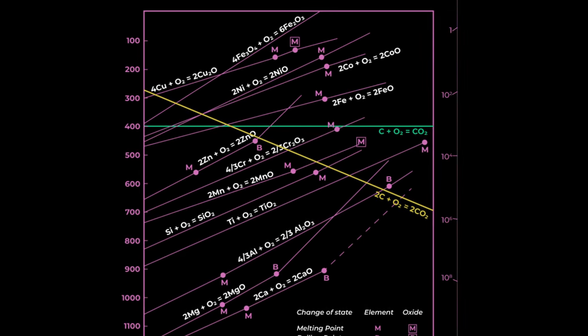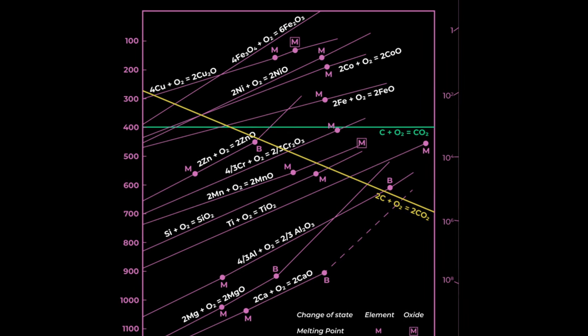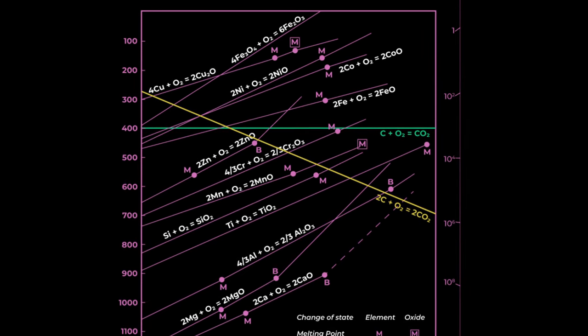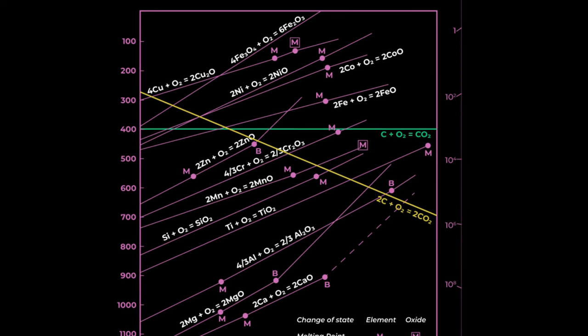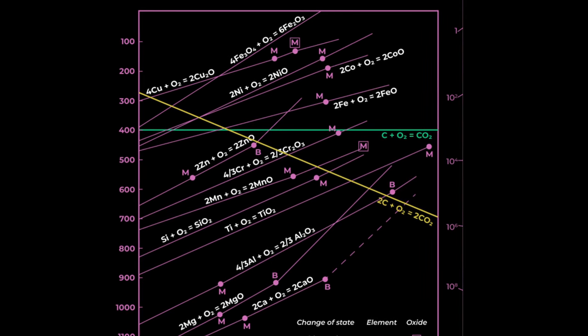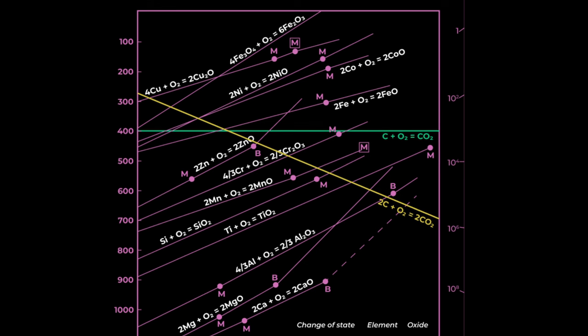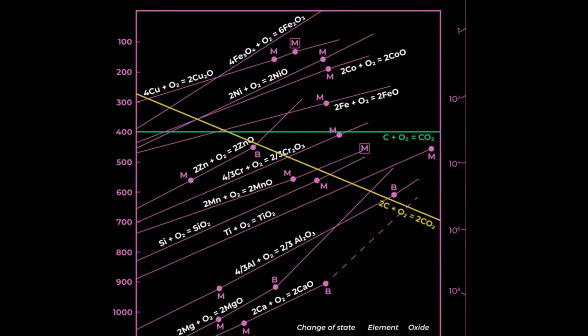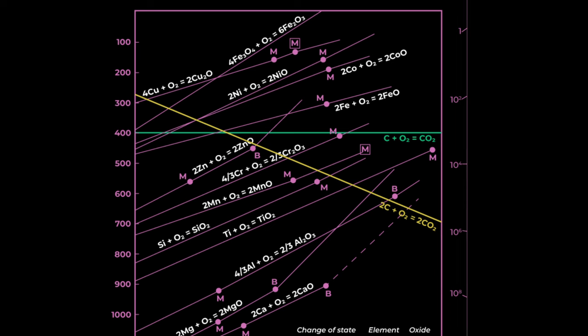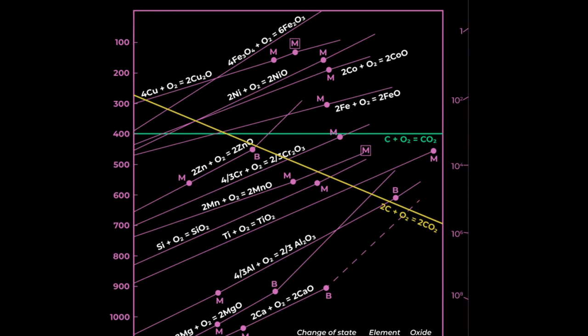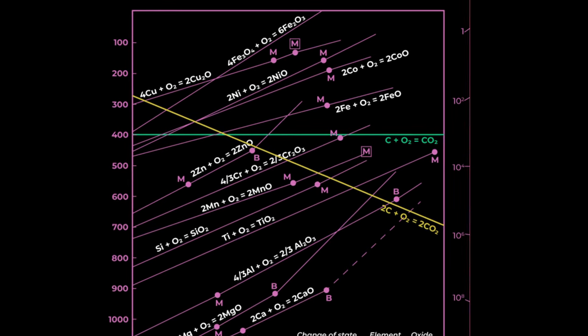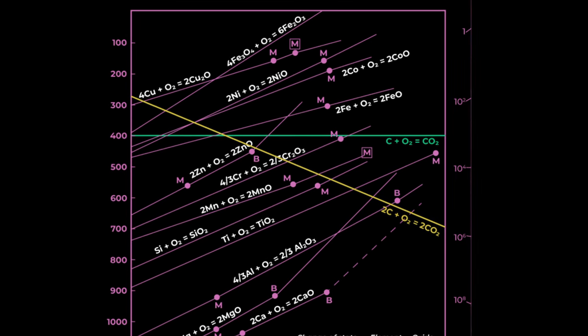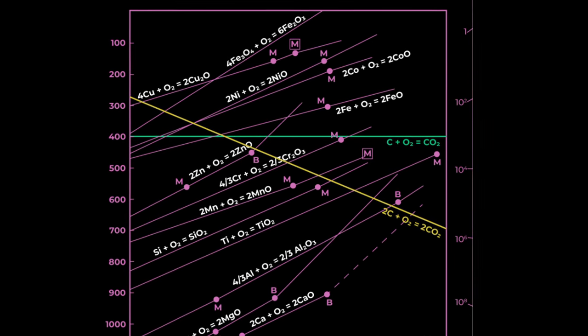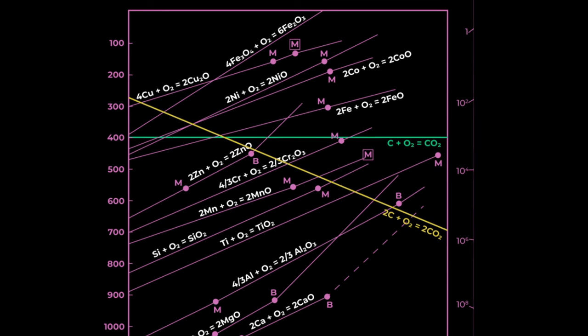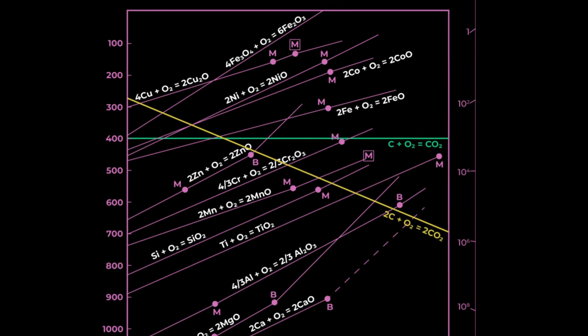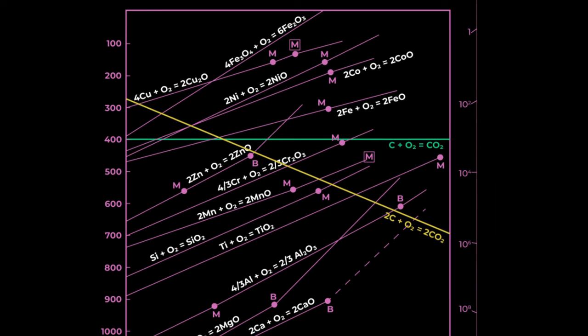But if there is a lot of iron oxide and only a little bit of reducing agents, let's say half for simplicity's sake, so there's twice as much iron oxide as things that will reduce it, then when we heat the regolith to 1600 C in a solar oven, we'll yield some pure iron, but half of it will still be an oxide. But if we add more reducing agents, then there will be more competition for the same amounts of oxygen and will yield more pure iron. If there are twice as many reducing agents as iron, then we'll yield pure iron and the next thing below it, likely nickel, so we'll get an iron-nickel alloy.